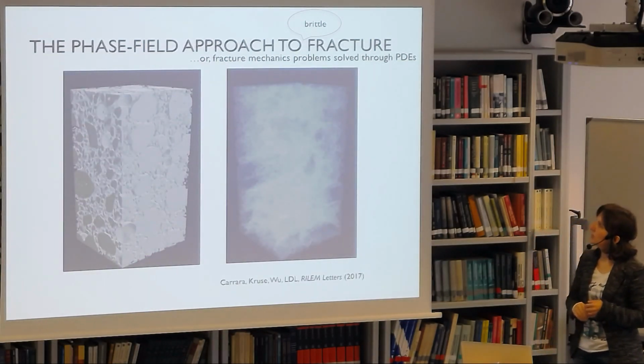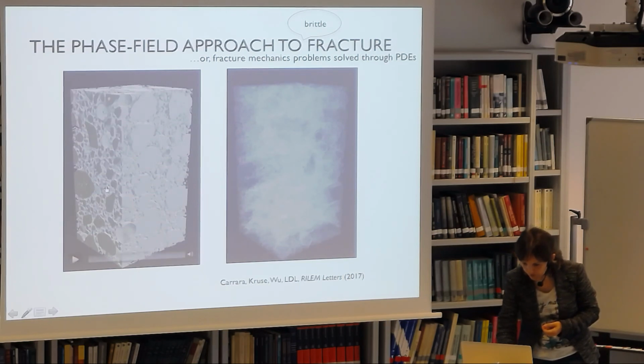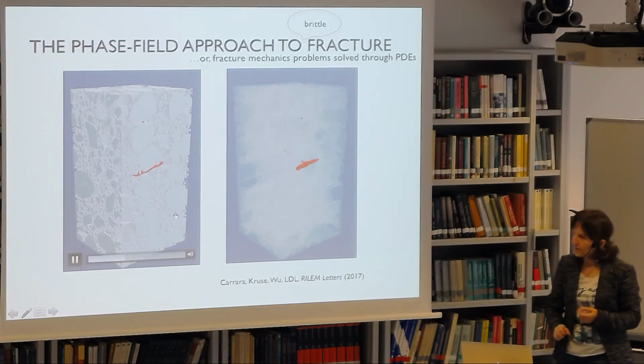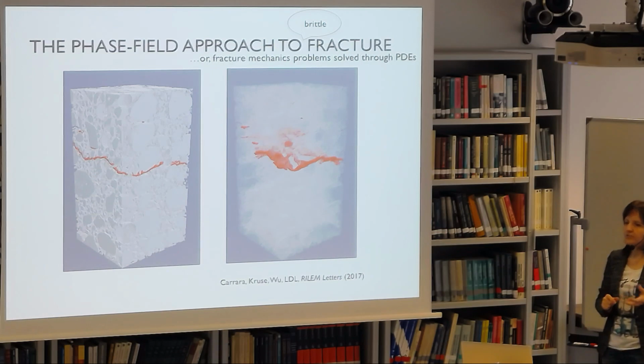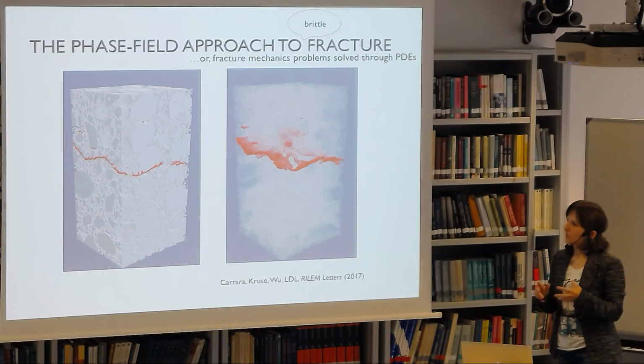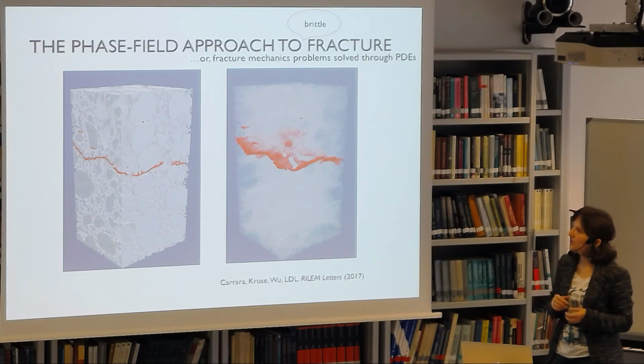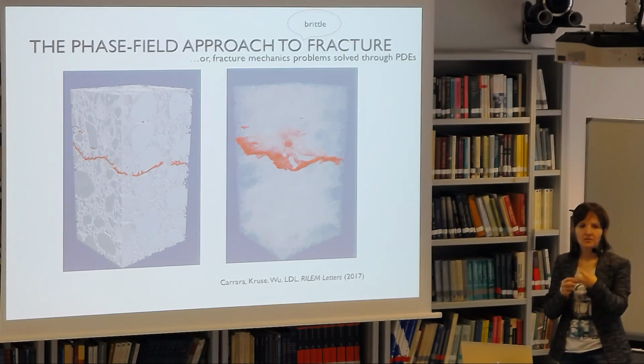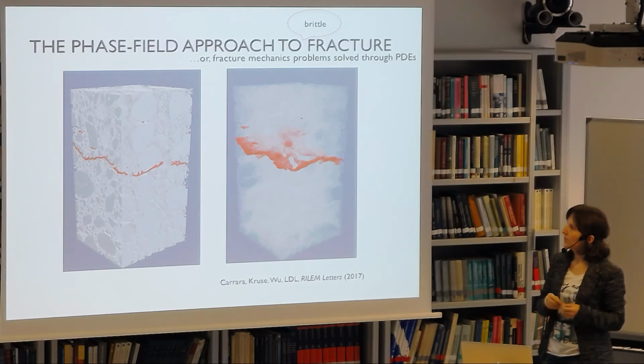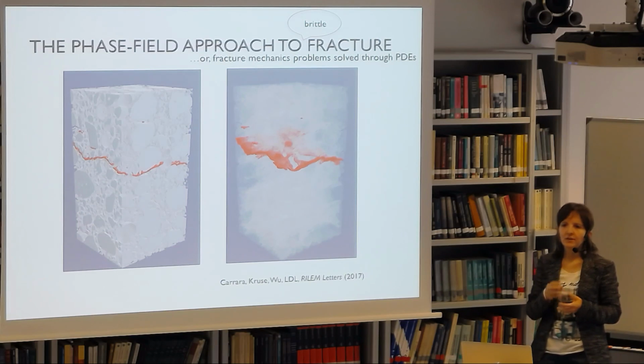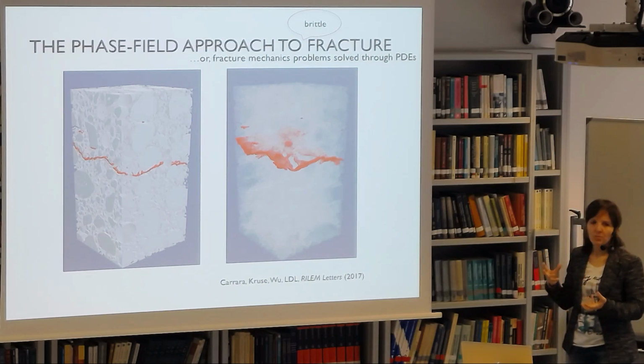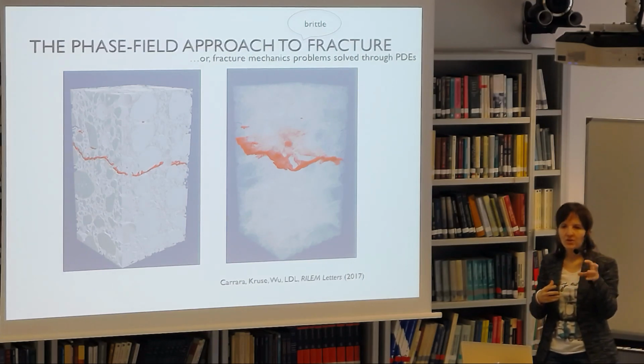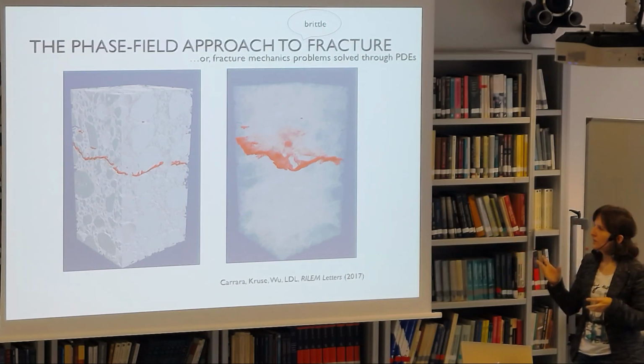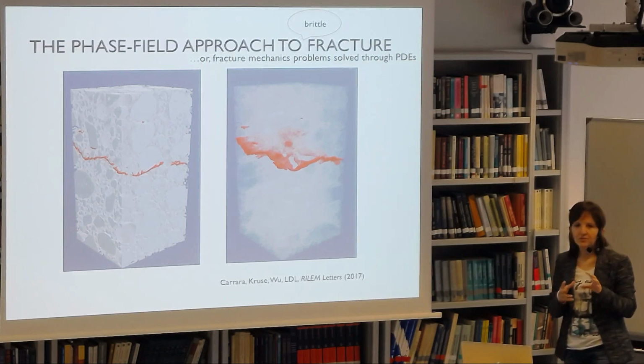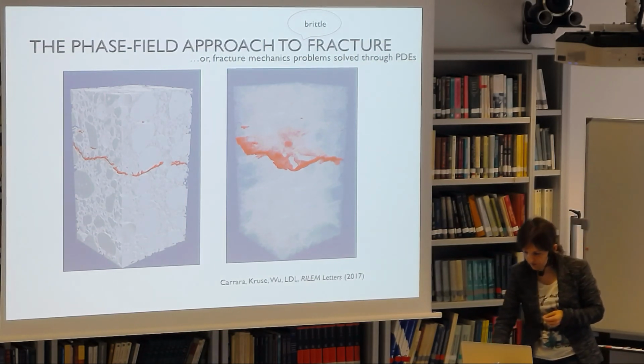But just to show you that this approach can be used also for very large problems, I'm showing you the last large problem that we have been solving in my group. This is a specimen of concrete that comes out from a CT, from a computer tomograph. So this is the real geometry. The contrast is not very good in the image, but here you can see aggregates, cement paste, pores. These are all resolved, and then with the phase field applied to the cement paste, you can really find very complex crack patterns, which we can observe in the tomograph and at the same time predict with the simulations. And these are simulations with more or less 500 million degrees of freedom, so they are quite heavy simulations.